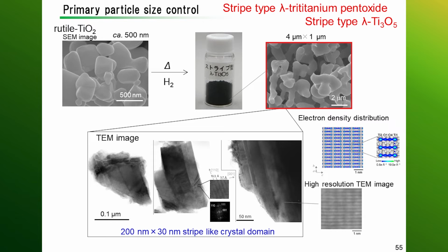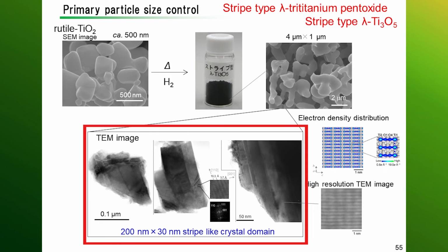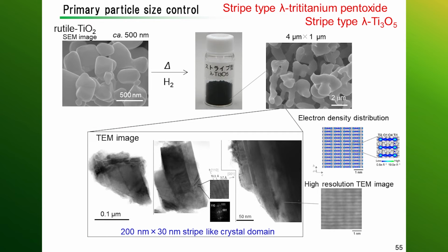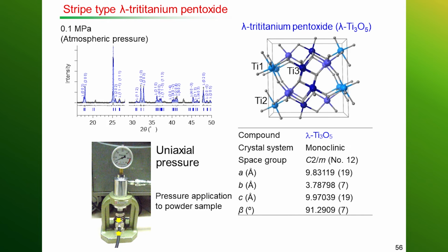But if you look inside, this is a TEM photograph. If you look at it with a transmission electron microscope called TEM, even though the particle size is large, such as 200 nanometers and 30 nanometers, the crystal size is much larger, but packed tightly. And this can be produced in large quantities. At present, almost all domestic manufacturers can produce this lambda titanium pentoxide. It didn't exist before, but now that it's been found, everyone can make it.